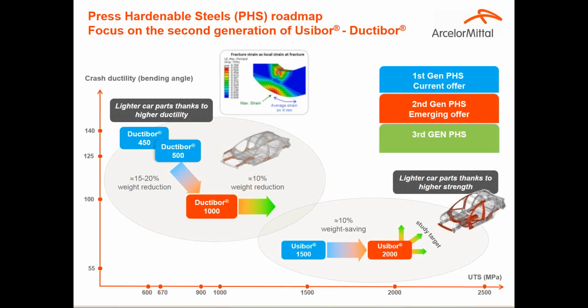The evolution of the PHS grades for, as I already said, absorption of energy and anti-intrusion is shown in the graph. And you see the two new grades developed by ArcelorMittal, Ductibor 1000 and Usibor 2000, today available and industrialized, that can provide around 15-20% weight reduction on the left-hand side for the energy absorption, and around 10% weight saving for the anti-intrusion. One important thing is that these new grades have been developed to be stamped and processed, I mean welded and assembled, using exactly the same processes used today. There are no changes in the lines.